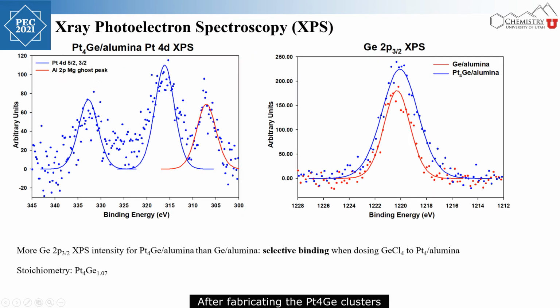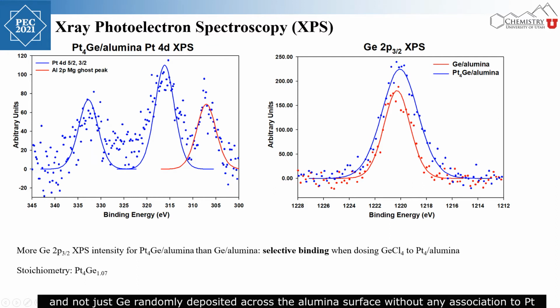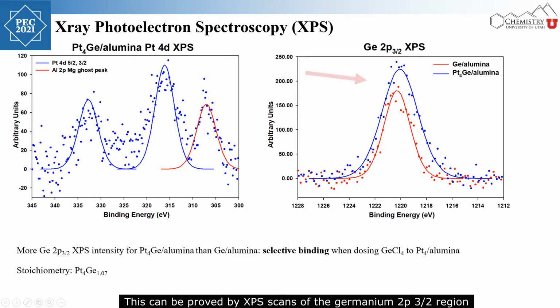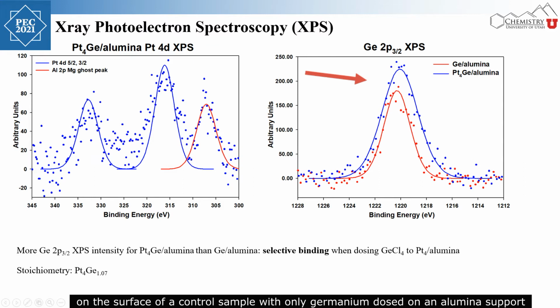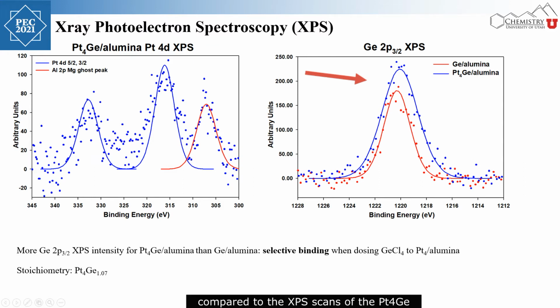After fabricating the platinum-4 germanium clusters, we need to know whether we actually incorporated the germanium into the platinum and not just germanium randomly deposited across the alumina surface without any association to platinum. This can be proved by XPS scans of the germanium 2p3/2 region on the surface of a control sample with only germanium dosed on an alumina support, compared to the XPS scans of the platinum-4 germanium.